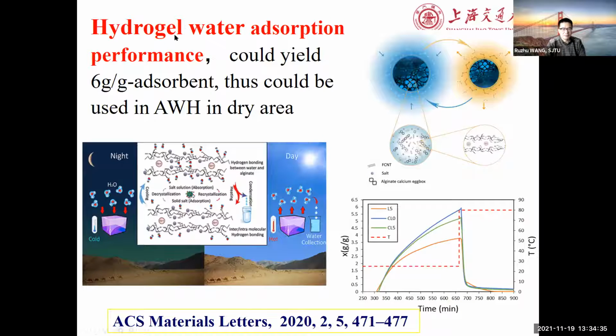So also we did this kind of work with hydrogel water adsorption, and 1 gram of hydrogel could get about 6 grams of water from the atmospheric air. So in this case, it's very good to be considered for use in dry areas, especially in some arid regions, desert areas. So this is the real test, and this was published in ACS Materials Letters.